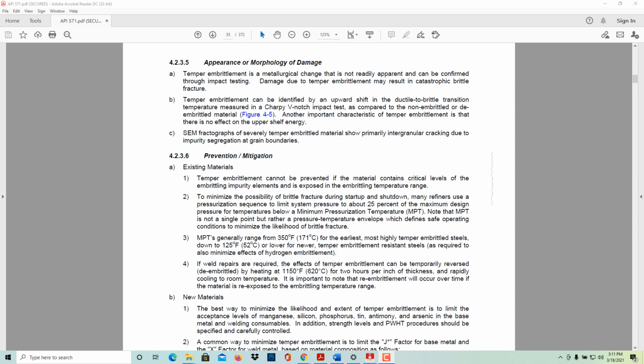Morphology of damage and appearance. Temper embrittlement is a metallurgical change that is not readily apparent and can be confirmed through impact testing. Damage due to temper embrittlement can result in catastrophic brittle fracture. Temper embrittlement can be identified by the upward shift in the ductile to brittle transition temperature measured by the Charpy V-notch impact test as compared to the non-embrittled or de-embrittled materials.